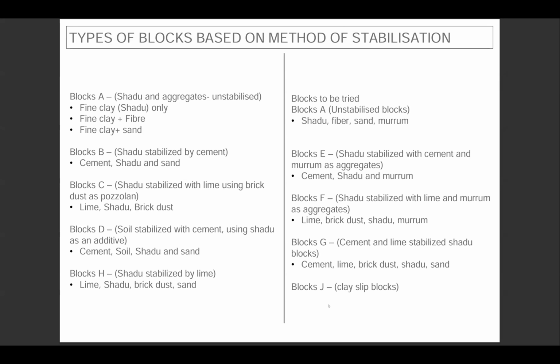Then we also experimented using shadow along with lime and brick dust. Lime and brick dust is something that we regularly use in many of our structures. So we wanted to understand what the addition of shadow does to a tried and tested mix like lime and brick dust, which has been used through generations now. Then the next lot of testing was soil stabilized with cement, but using the shadow as an additive, not a major portion of the soil, just as an additive. And then a mixture of all these, using a mixture of sand and brick dust along with lime and shadow. So this is what we did.